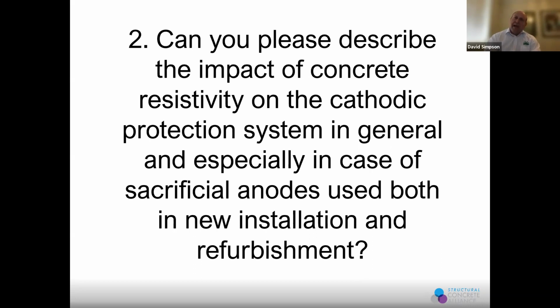When you're looking at repair materials going into a structure for ICCP, my personal preference, and the guys may jump in here, is always to go with something with a higher resistivity. Typically, you want something that's similar to the parent concrete, if not higher, because when you do the repair, you're cutting out all the chloride contaminated concrete and stopping corrosion. So you don't really need current going to the steel in the repair. You want the current passing to the remainder of the concrete where you still have chlorides and that corrosion risk. So those are probably the two broad ones from a repair situation for impressed current cathodic protection. From a galvanic perspective, things have changed quite a lot, I think, over the past 20 years.